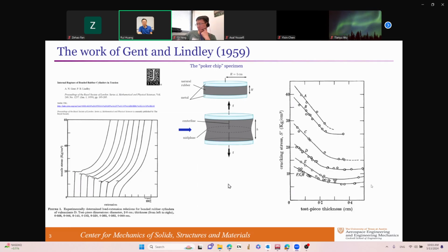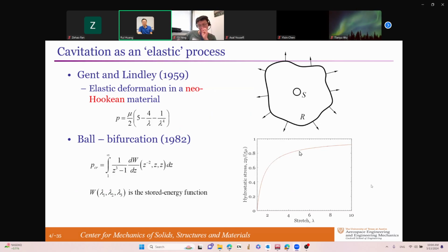He also measured the load at which this happens and found that in different materials, they exhibit a similar behavior, that as the thickness increases, the critical stress necessary to pop the flaw decreases and reaches an eventual plateau. There's an immediate result that comes from here. If you want a high strength for your adhesive, make the adhesive thickness very small. Right? Don't need any analysis to prove that. The experiments tell you automatically.